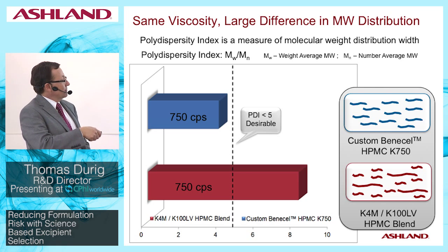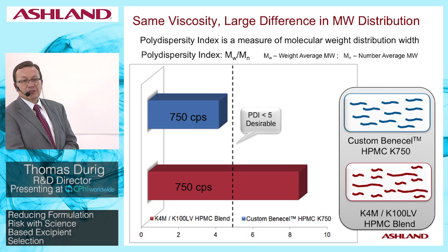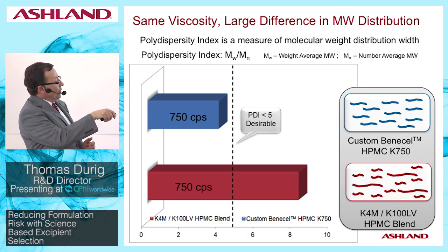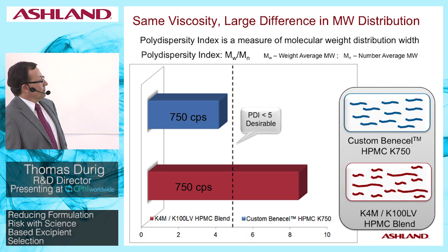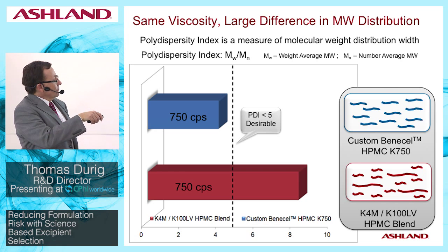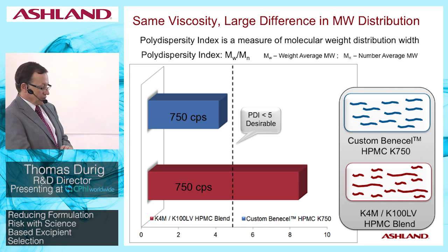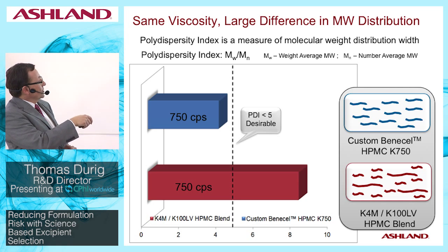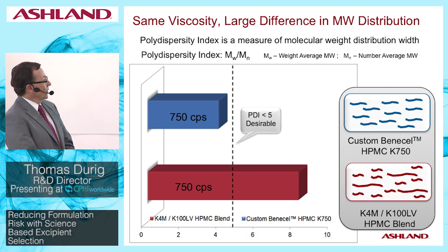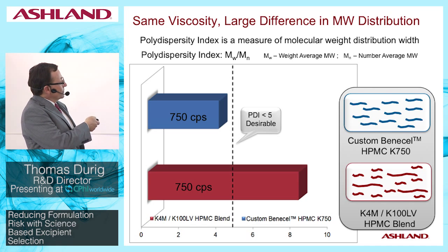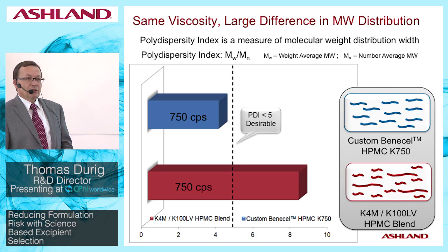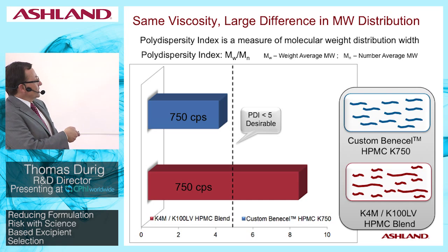This is very different from if we actually custom made an HPMC polymer that has exactly 750 centipoise as its viscosity, achieving that through an intermediate polymer chain length as shown here in the top left corner. And this is physically obviously quite different. Here we would have a more uniform and narrow molecular weight distribution. Molecular weight distribution tends to be measured as polydispersity index, which is the ratio of the weight average and number average molecular weight. And typically, in most polymer scientists' book of rules of thumb, we would say a polydispersity index of less than 5 is usually regarded as relatively narrow and not too wide. And you can see here clearly that if we use this polymer blend where we have the bimodal distribution, we get a polydispersity index of about 8, contrasting that with the custom-made HPMC of 750 centipoise, half the polydispersity index.